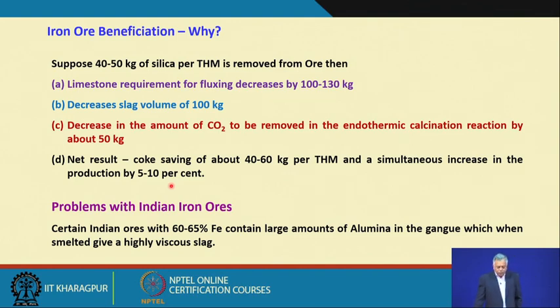So, only by removing 4 to 5% of silica, that is 40 to 50 kg of silica per ton of hot metal, in 1000 kg of hot metal, will give you a benefit of increased production by 5 to 10%. Whether it is 5 or 10%, that depends on other characteristics of your iron ore and your impurities and other associated things.